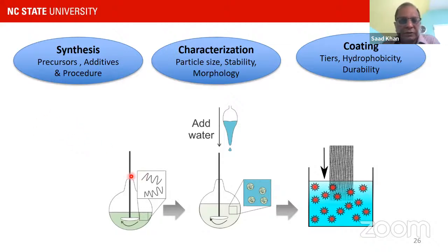So we would have the precursors, mix them in sequence, some of them together. And then eventually what you would get is dispersions, and so we'd use an anti-solvent, water, and you would end up with these dispersed particles or dispersions of these systems. They wanted a water dispersible system. And then we would coat them on fabrics. And this is a dip coating approach, and then we would heat them and dry them.